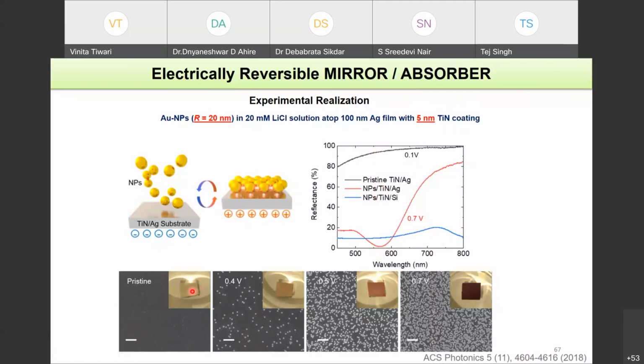You see, pristine silver, it is very reflective, but it has got a titanium nitride, so it is giving a bit of golden reflection. Titanium nitride looks like gold. Okay, and then slowly when you are increasing the potential, some nanoparticles are coming and sitting. You increase to 0.5, more nanoparticles. See, these white dots are nothing but these gold nanospheres. Okay, these are the SEM images. So at 0.7 volt, you see they are very densely packed.